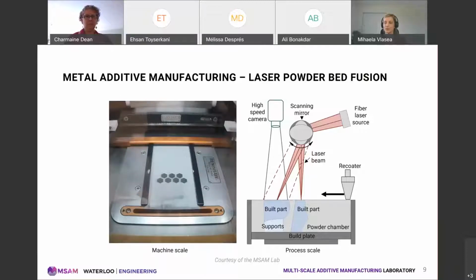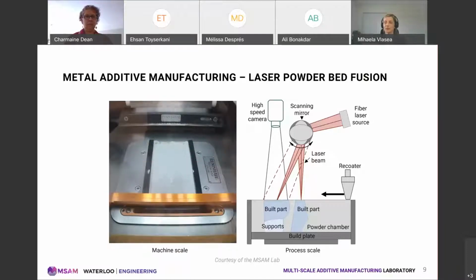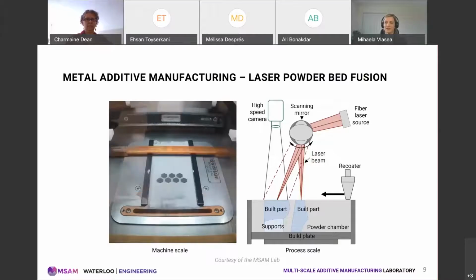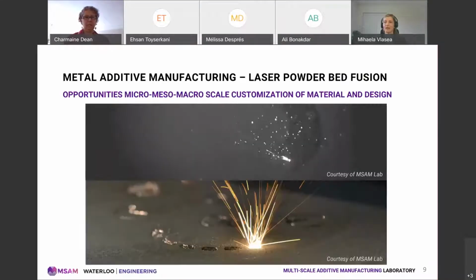This is a thermal process which requires support structures not only to anchor the part to the build plate, but also to ensure heat transfer, reduce part curling, and reduce porosity defects. For laser powder bed fusion, the laser material interaction is in essence a micro-welding process, where the material undergoes melting, vaporization, and often ejection. With each added layer, the material is exposed to melting, solidification, and thermal cycling, influencing the microstructure and material properties of the final component.